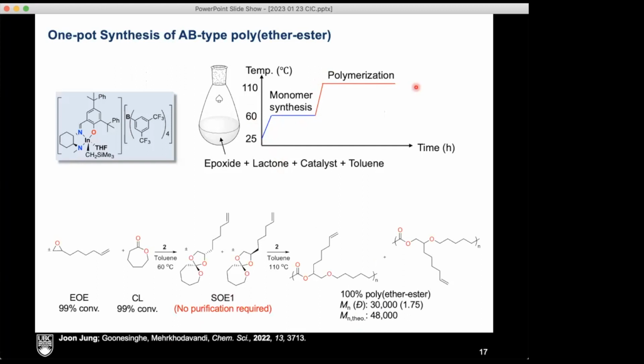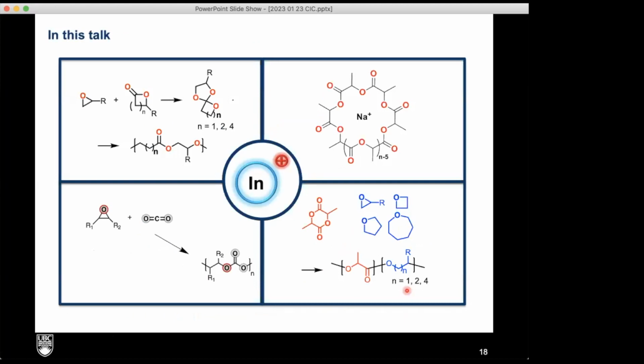And he was able to do this reaction without having to isolate and purify this monomer, and was able to generate these polymers here. And depending on the molecular weight, he can actually then cross-link them, play around with that. And this is something that is ongoing in the group. We're interested in what other functionality we can incorporate here, what we can do with cross-linking. There's a whole study going on about how to understand the mechanism of this reaction, and that's going to be coming up. Okay, so that's the first story.